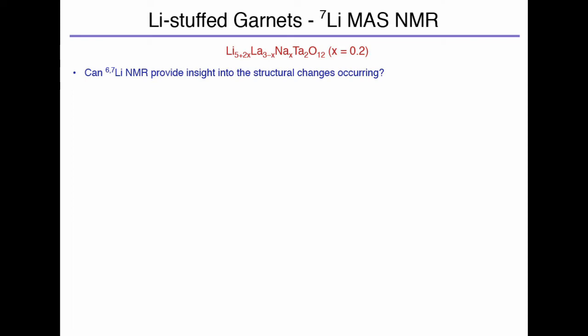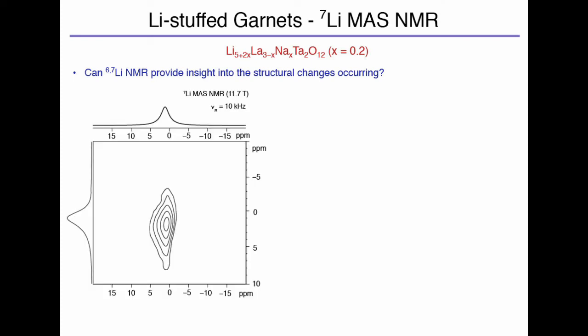So the beauty about NMR is you can look at structure indirectly, so you don't have to just look at the element specifically that you're interested in, you can also look at the other elements around. So lithium is also in here. So we can start by doing a lithium-7 experiment. Again, the top spectrum here is just a conventional one-dimensional experiment, and you can see it's a relatively broad line shape. It doesn't tell us much.